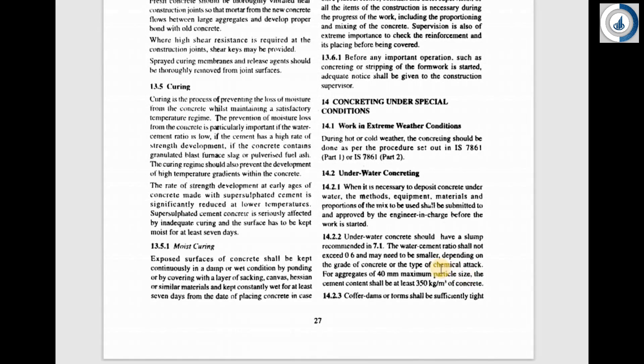The code specifies that the water-cement ratio should not exceed 0.6. Depending upon the type of water present and the chemical attack, it should be less than or equal to 0.6. For aggregate with a 40 mm maximum particle size, the cement content shall be at least 350 kg per cubic metre of concrete.